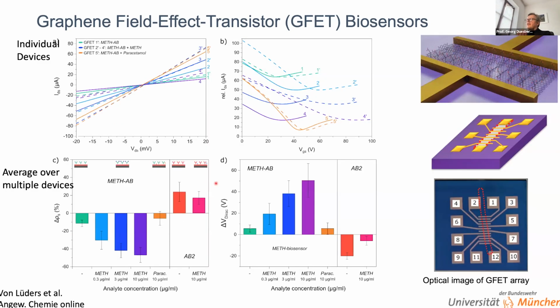But in the next slide, I show you that our meth antibody functionalized graphene sensors react quite nicely towards given analyte concentrations, which is shown here. You can see the shifts of the Dirac point, or the changes of the resistivity of our sensors, with the exposure to the analyte. But let's go to the graphs where we averaged over roughly 60 transistors we made, and you can see a nice dependence on the meth concentration here. And as a cross-check, we use paracetamol, where you didn't see any change in conductivity.